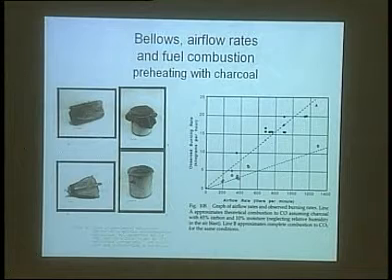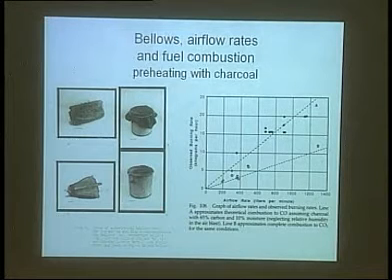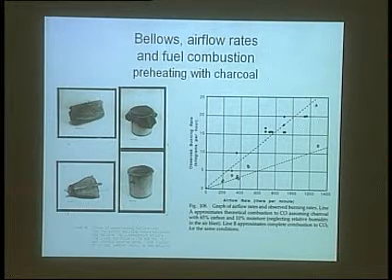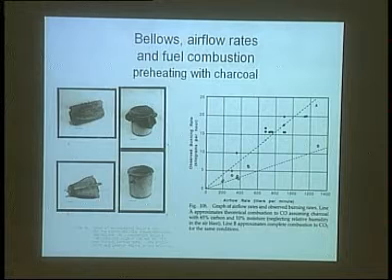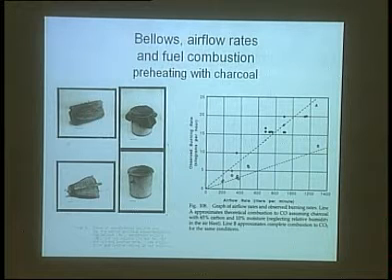Also, it's very interesting that when one would shift weight from one bellow to the next, you get much further penetration of air into the furnace. So that also helps solve some of the problems that we had encountered with the fire brick. Okay? The concertina bellows, well, those are just as effective, but they're anachronistic for the time, and you can make this type of bellow to whatever size you want. Okay? But it's the pot bellows that are the important aspect, because that allowed the dimensions of the furnace, the volumes of the slag, and all these materials to be processed.